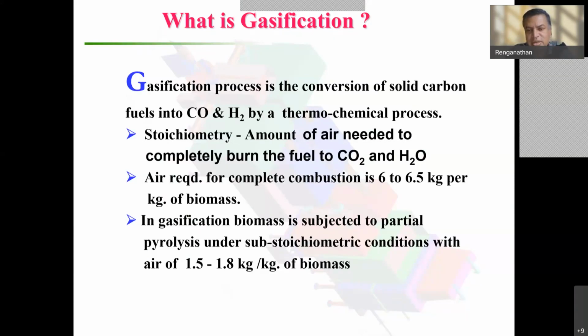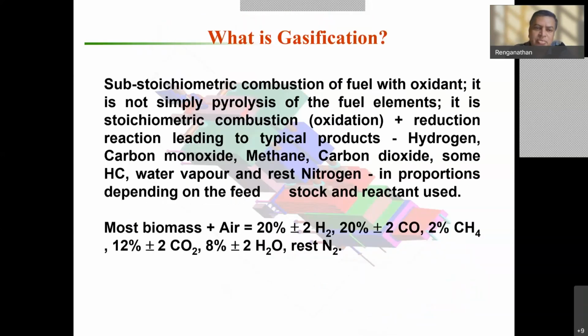In gasification, we do partial pyrolysis under substoichiometric conditions, where the amount of air that is used is only 1.5 to 1.8 kilograms per kilogram of biomass. So this way, we get hydrogen, carbon monoxide, methane, carbon dioxide, water vapor, and nitrogen when you substoichiometrically combust the biomass.